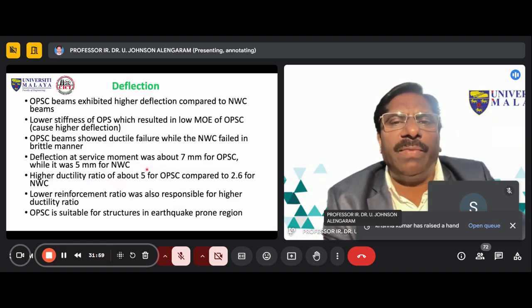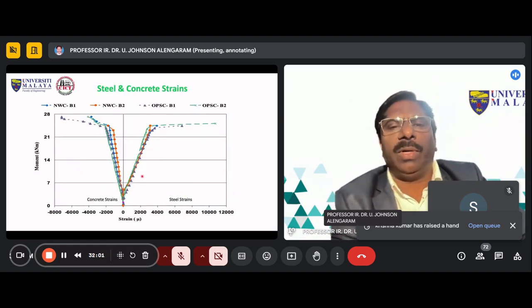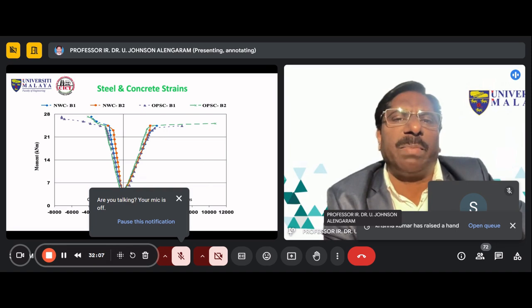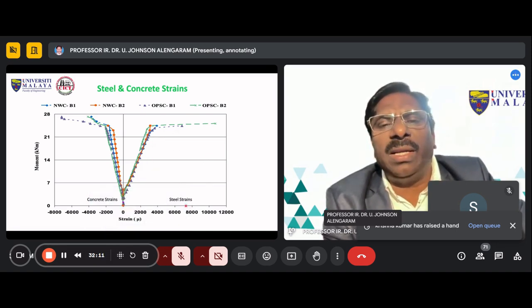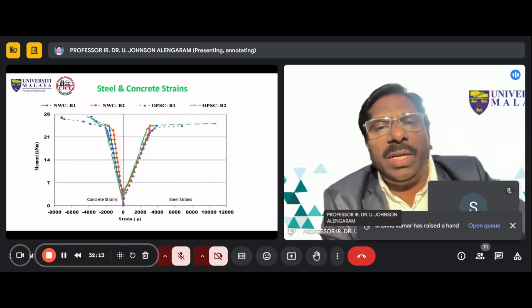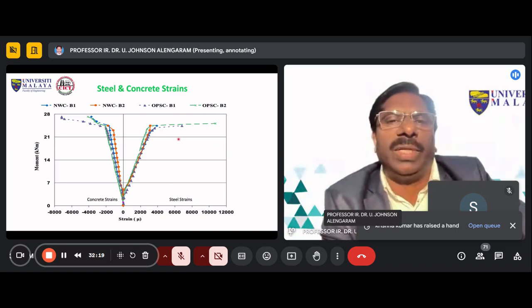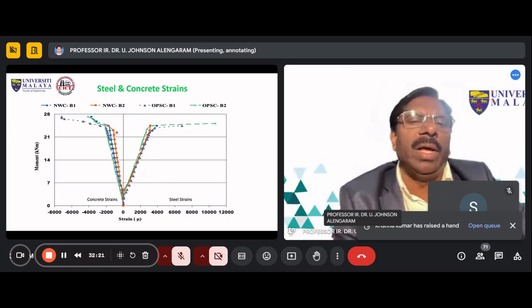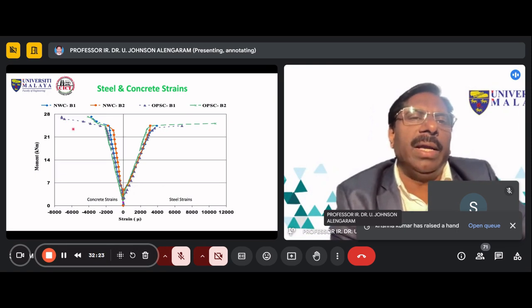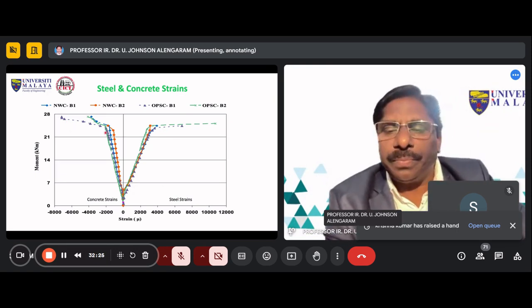So what we did was, if you look at the micro strains in the lightweight concrete, almost 10,000 micro strains compared to 3,000. Normally we expect 3,000 micro strain, and the steel will yield. But this concrete did not yield. After yielding, it did not break, but continued to almost 8,000 or even 10,000 micro strain compared to the normal weight concrete beam. Even the concrete strain was higher here, you can see.